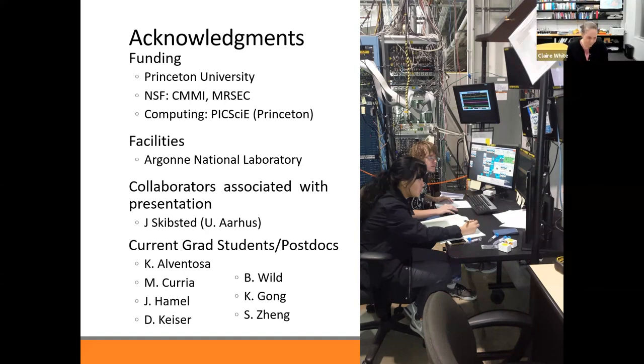Yeah, that's a very good question. So we use high energy X-rays around 60 kilo electron volts. It is known for X-rays that you can get significant beam damage for materials in what's known as the water window, which I don't remember the exact values, but it could be around 1 to 2 kilo electron volts. So for carbon and water systems, if you're using X-rays in that region, you want to be very careful because you are ending up with beam damage. From the studies that we've done, whereby we expose the sample to X-rays and look at changes over time, we haven't seen any indication that, between a very short exposure and longer exposures, we're getting a change in the scattering pattern, which would indicate a change in the structure due to beam damage.